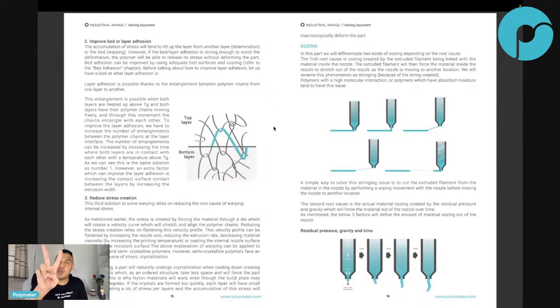And that's why there are 2 types of annealing, because I always hear annealing is about crystallization. Oh, annealing to crystallize, annealing to crystallize. But there are 2 types of annealing. Annealing is heating up a part, right? But there are 2 reasons why you would anneal a printed part. Reason number 1, crystallize your part, finish the crystallization process. Reason number 2, remove the residual stress that we talked about.